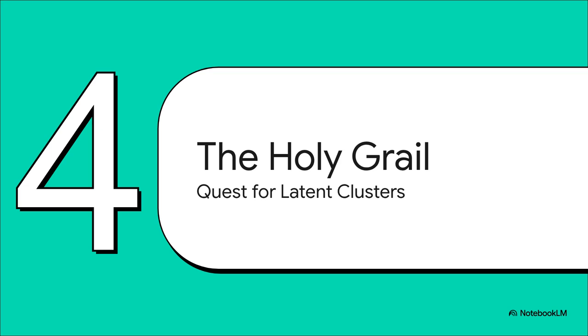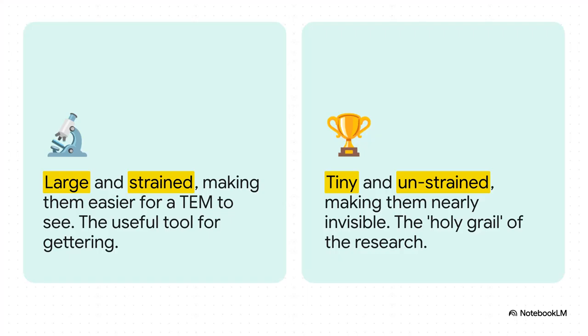So, being able to see those final, fully grown precipitates is one thing, but the real holy grail of this whole field is to see them before they grow, to actually find the invisible seeds that these crucial traps grow from. And this slide really breaks down the challenge. On one side, you've got the grown precipitates. They're the workhorses, they're large, and they actually stretch and strain the silicon around them, which thankfully makes them pretty easy to see in the microscope.